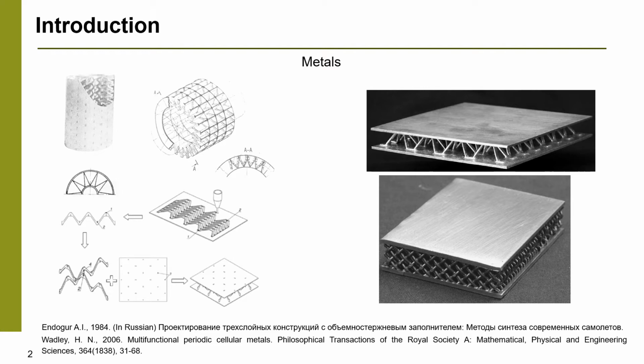For the strength analysis and analytical prediction of buckling load of the lattices were provided. And in addition, from mechanical testing, it was observed that there is debonding between outer shells and the core due to poor solder joint properties.